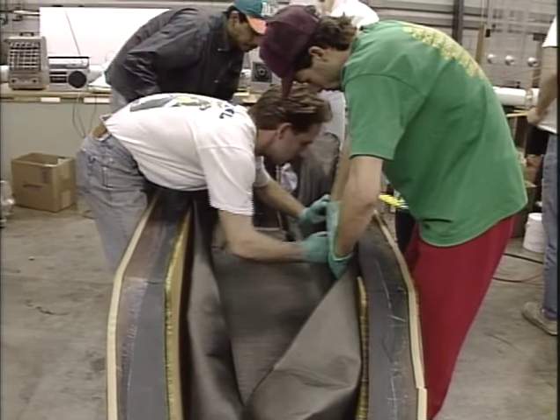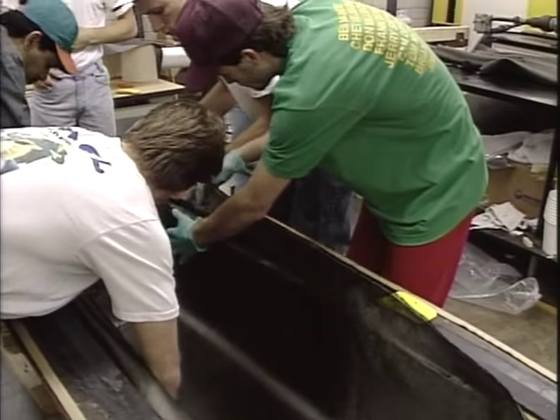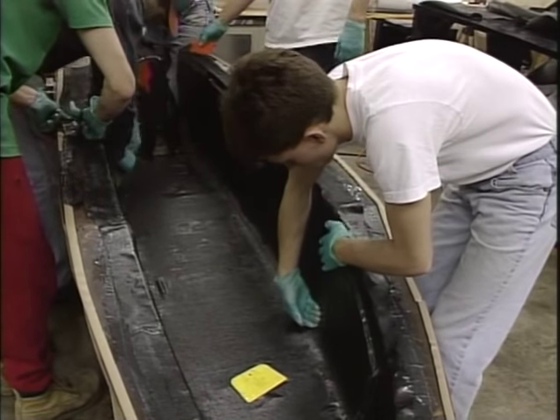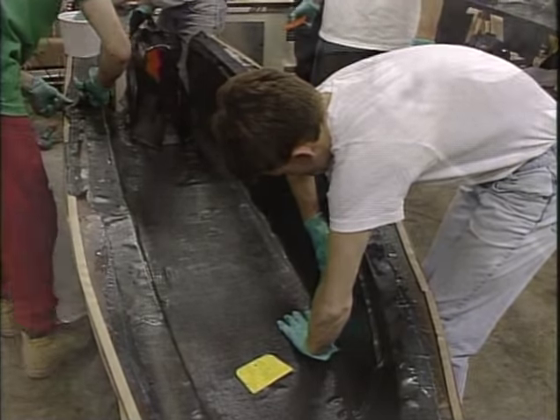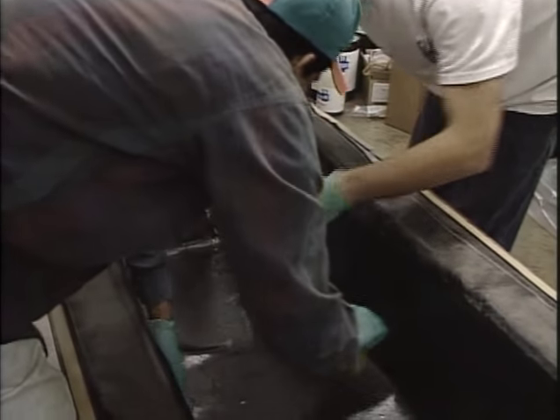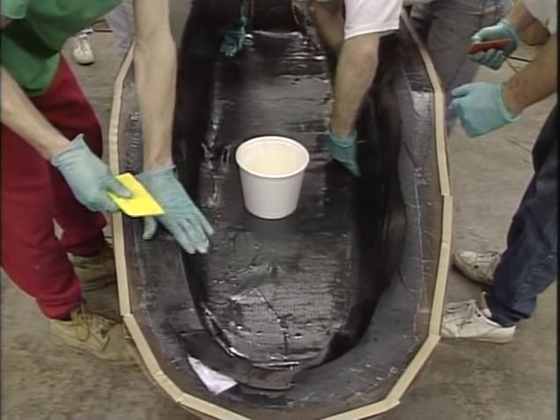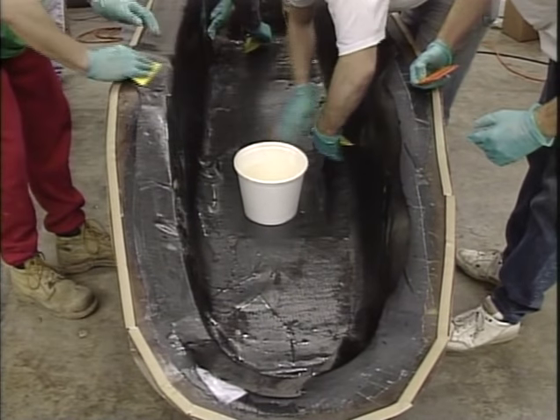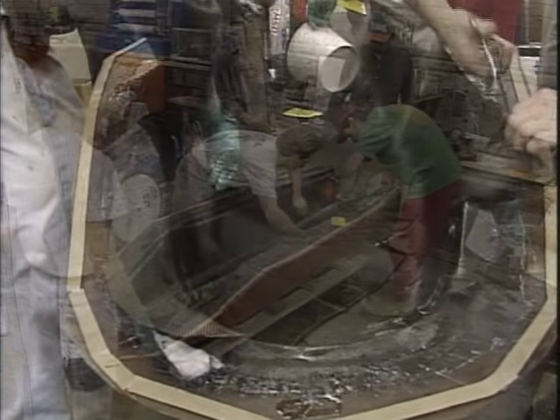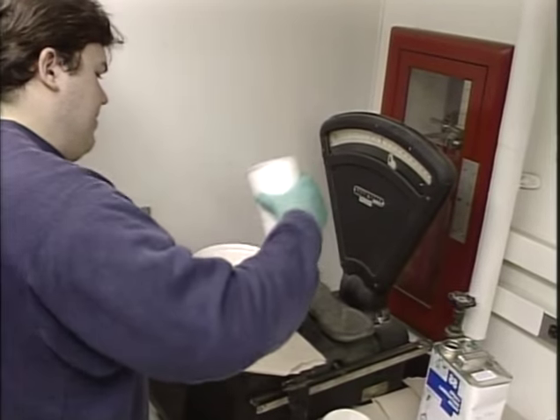The first of the inner skin plies was a zero-degree layer of carbon fiber, laid in dry and wet out with resin from above. It was important to thoroughly saturate this layer, but without applying so much resin that it would flow profusely into the cells of the core. However, most resin that did run through the fabric into the honeycomb would be sucked back up into the fabric by the vacuum process. This stage is tricky because you need the fabric to contact all surfaces below it, but air pockets still appear because the honeycomb is filled with air — these will also be removed during vacuum bagging. Resin was still being mixed carefully, batch by batch, as needed for each layer.